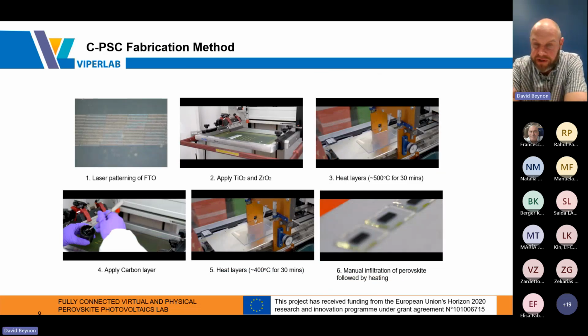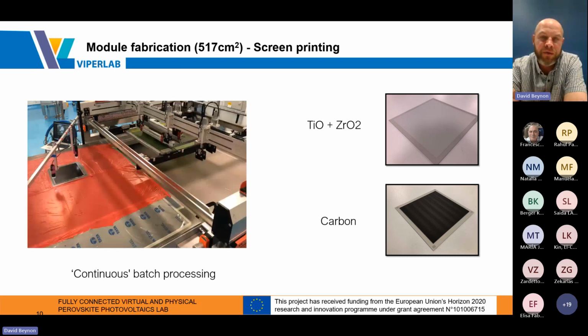And on our lab scale devices, we process that through all stages using laser patterning of the FTO. We then use a screen printing process, and we have a small format, so basically A4 size screen printing to put down the titanium and zirconia. Heat that for up to 500 degrees, then apply the carbon, go through with screen printing, go through another heating stage before we manually infiltrate those. But we also have facilities to go up to large-scale module fabrication.